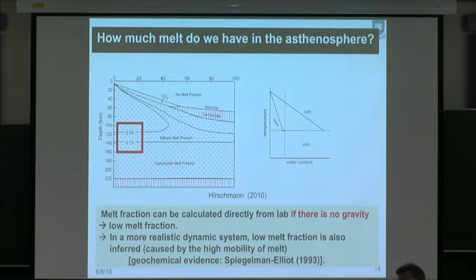This is the unrealistic case of no gravity. But even with gravity, you can easily calculate the melt you expect. The amount of melt you expect is very small, simply because melt migration is so fast. Mark Spiegelman did very nice work to confirm this from geochemical observations 23 years ago. So the bottom line is that the amount of melt we expect in many places, including the asthenosphere, is very, very small.